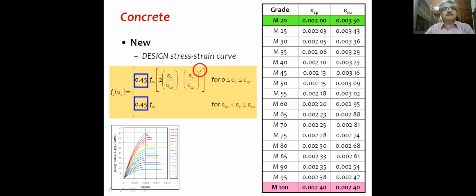Probably it will be simple to give one simple expression for all of it and just use the quadratic equation which was there originally, instead of changing the power based on grades. So at least one thing is taken out of the equation. But this is done considering that the ultimate strength capacity is more or less maintained, so that the ultimate estimate of strength is not significantly changed. But this is how the strain values are decreasing.